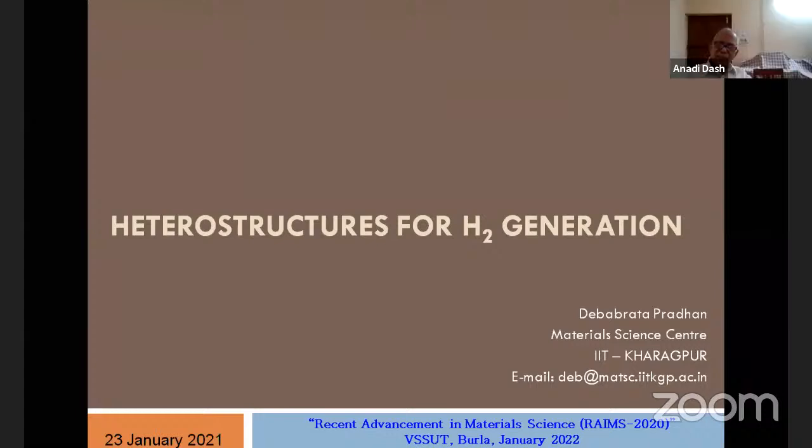Sir, anything else? Did your iodine not create any problem in the use of HI as a reducing agent? Yes, sir. Actually, that was a really nice question because when you do the reduction with hydroiodic acid, iodine remains on the surface also. After washing with dilute HCl, trying to wash it out, still some ions remain on the graphene surface. But when you checked the supercapacitance property, it is not a disadvantage because it has some pseudocapacitive behavior, it is helping. So that's what I wanted to know.